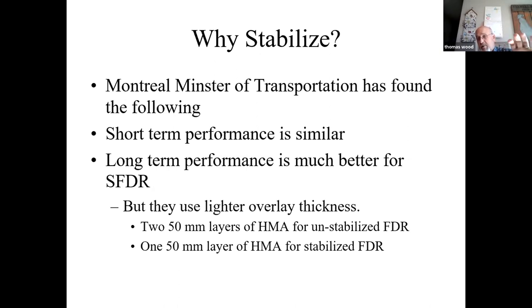But now they're getting the test sections out long enough that they're getting toward the end of their life, that they're seeing a dramatic improvement on the stabilized, even though it's got half as much HMA on it versus the unstabilized. To me, stabilized full depth reclamation is a tool that's way underutilized because it allows you to build the strength down into your pavement so that you keep your in slopes from getting too steep. If it helps you with elevation, there's a lot of benefits.